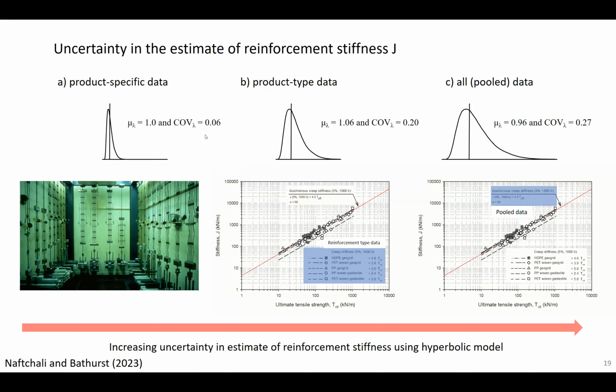If you know that your material is part of a class of materials of one type or another, then when you use this approximation that I showed you before for this linear approximation, your estimate of the stiffness will have a COV of say 20%. And if you just lump your product in with all the other data that we've got, then the uncertainty is about 27%. So this demonstrates that there is a practical benefit to actually carrying out product-specific creep testing, because you are rewarded with a better estimate of what that stiffness is.